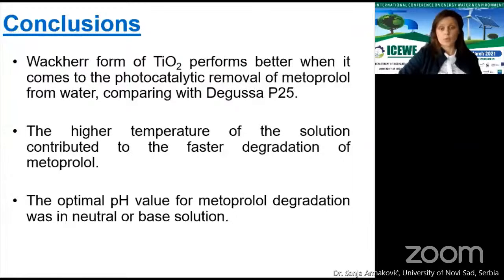What we can conclude and what we actually did: the study of photocatalytic degradation of metoprolol in the presence of commercially available forms of titanium dioxide has been performed. The study aims to evaluate this material's efficiency for removing metoprolol from water through analysis of the kinetics of photocatalytic degradation. This study also accompanies the investigation of the influence of temperature.